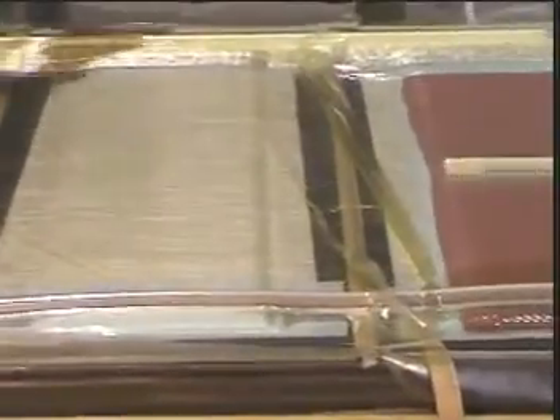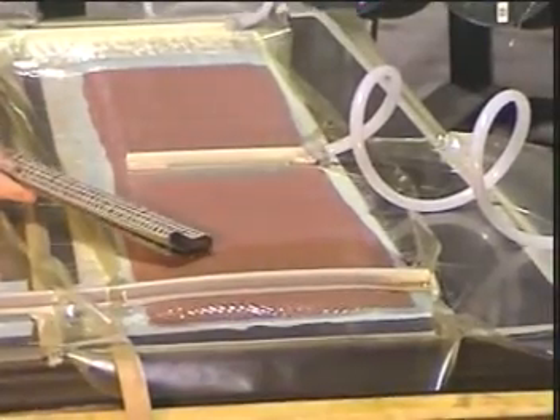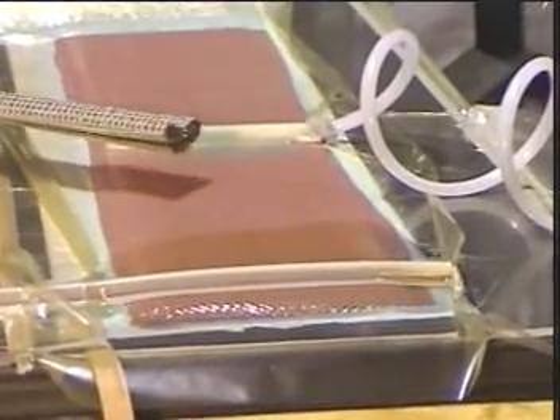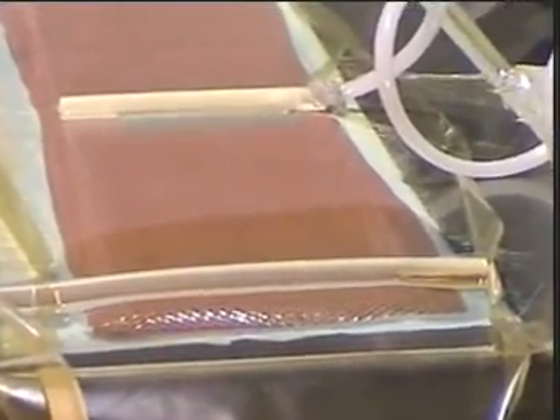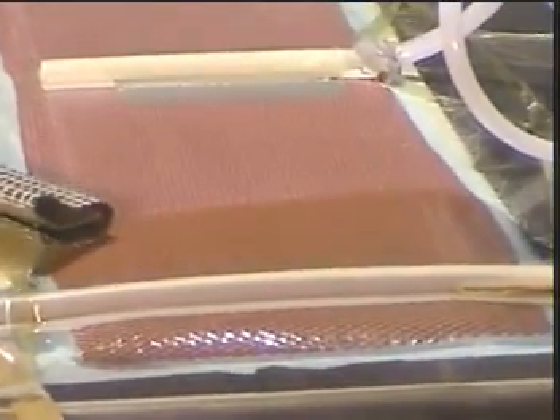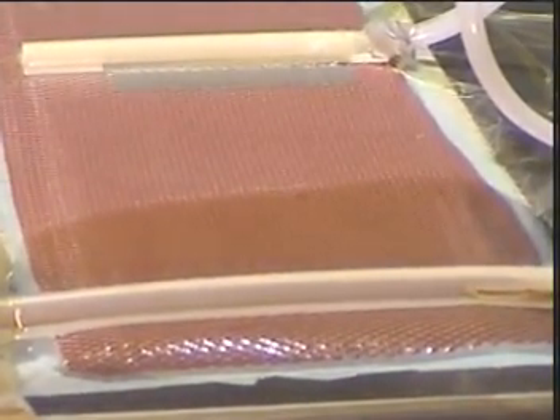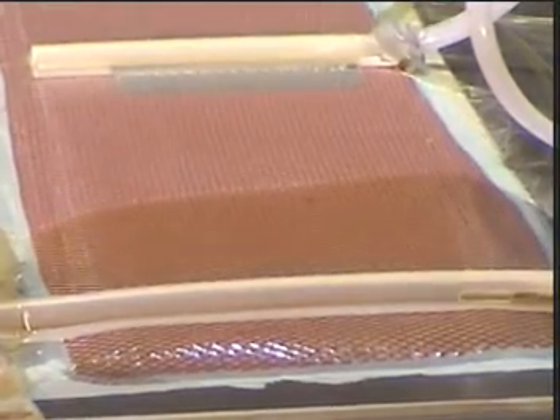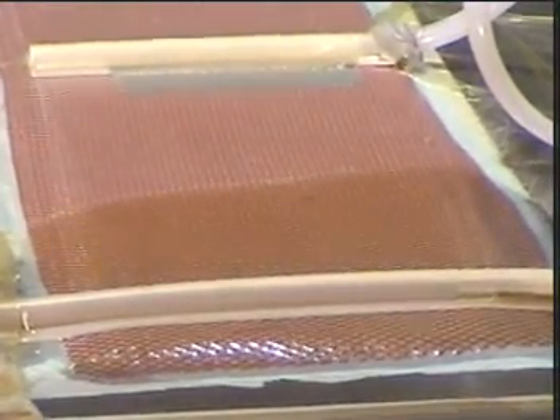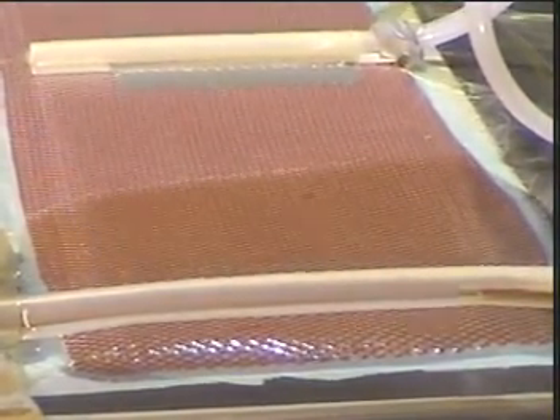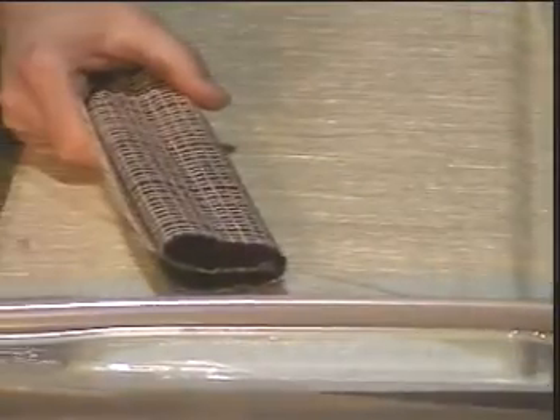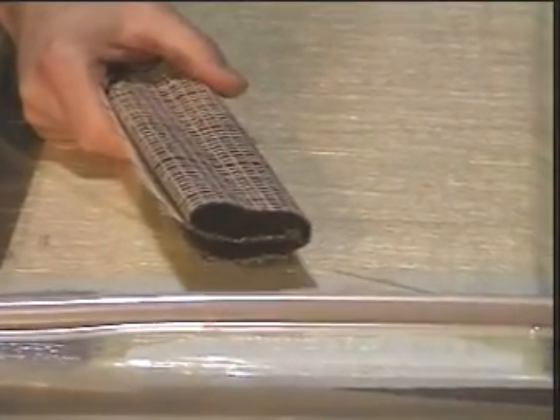Okay, you can see the panels filling. You can see the distribution media moving relatively quickly, where it's moving across the top of the laminate. One of the difficulties here with this particular laminate is it moves across the top, but then it has to move through the thickness, and you actually get quite a gradient of flow. You can see that the all-glass laminate, the resin's not moving at all. I mean, it's just kind of dead stuck.